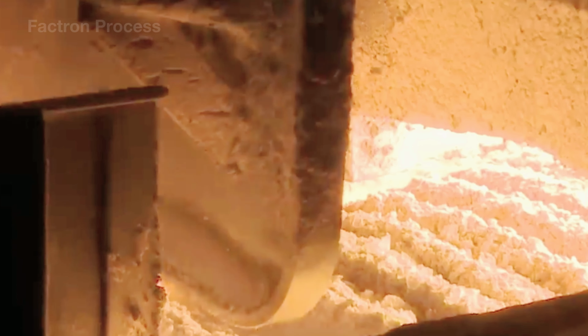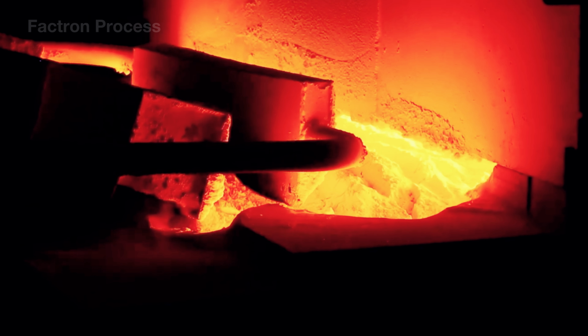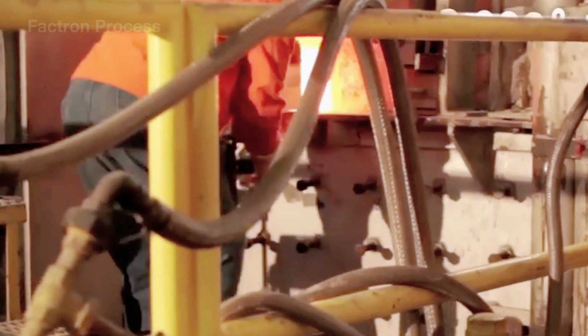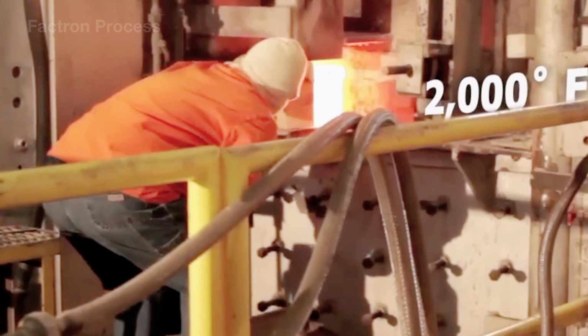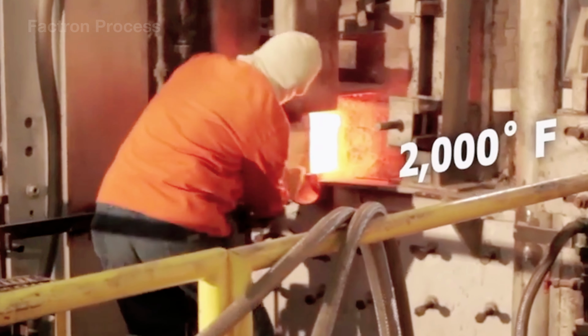A piece of ceramic that has not been removed may not melt. A little remaining metal can change the color. A small amount of organic contaminant can create air bubbles. In other words, the furnace does not forgive carelessness. The quality of a new bottle does not begin at the forming stage, but from every previous step of sorting,